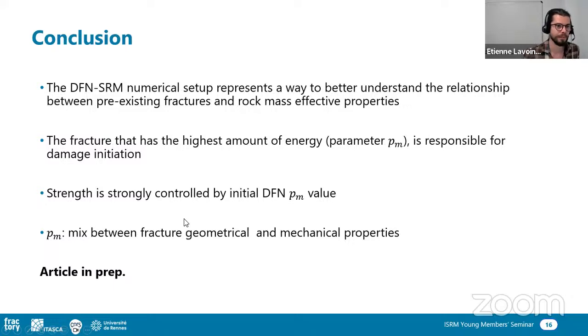So to conclude, we use the DFN SRM numerical setup, for discrete fracture network and synthetic rock mass, to better understand the relationship between the pre-existing fractures, so the natural fractures, in multi-scale environments, and relate it to rock mass effective properties, both elastic but also strength properties. This is still ongoing work on the strength properties. And what we have shown is that the fracture that has the highest amount of energy, which we characterize with the parameter PM, is responsible for the damage initiation, and that the strength of the fractured rock mass is strongly controlled by the initial value of PM, which is a mix between the fracture geometrical and mechanical properties.